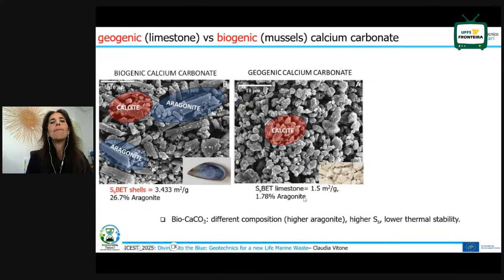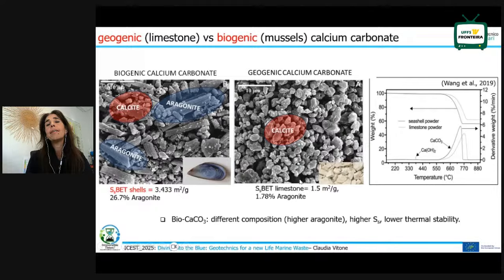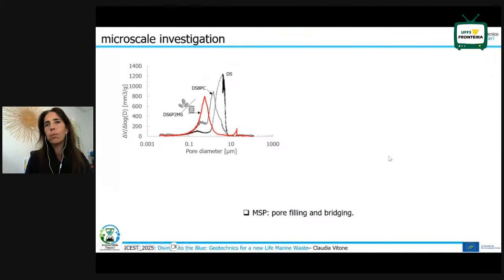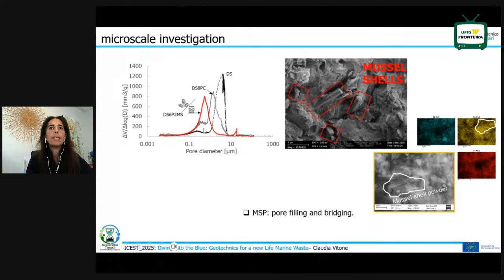So we have a higher specific surface, which means this material is more prone to react in engineering systems, and which also means that it is characterized by lower thermal stability compared to the geogenic one, which is again a good result. If we run MIP tests, so we inject mercury to understand the porosity of this material, and we compare the dredged sediment with the control mixture, and in red the mixture including also the shell powder with less cement, we observe that the main pore size is reducing, and from a bimodal mode we are shifting towards a monomodal pore size distribution.